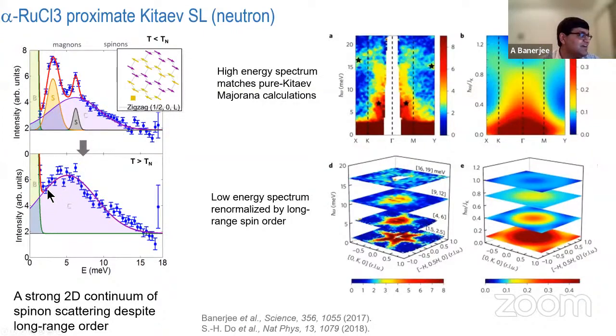It almost seems that you have an emergent incipient gap. And so you can map the states to what the Kitaev solution looks like. As it turns out, the higher energy spectrum basically looks like what you should expect from Kitaev's exact solution. So this is Kitaev's exact solution. This is the spectrum that people have measured in neutron scattering, including some of my own papers. And as you see, it matches very nicely. But the low energy spectrum doesn't quite match up so well.